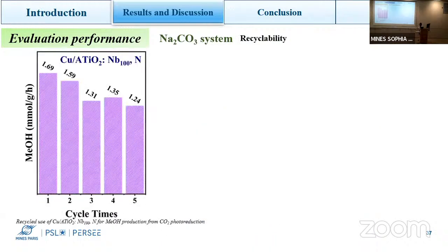And then we considered testing our best catalyst for its recyclability. The first two rounds remain a good value, and then the performance gets lower; we lose some activity. It still remains a good value, but we're losing some activity. So we're thinking about what happened during the reaction.